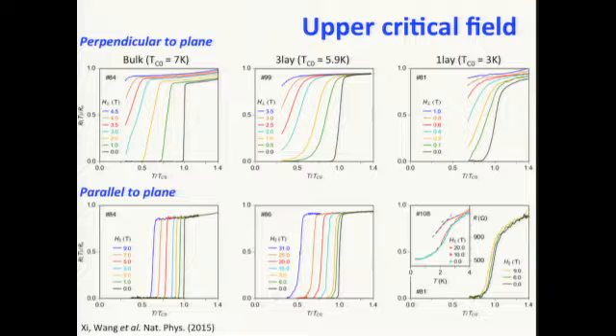The B field required to quench superconductivity in the monolayer is somewhat lower because of the lower TC in the material. On the other hand, if we put the material under a parallel magnetic field, the material turns out to be more resistant to the application of an external magnetic field. What I mean is that under 9 Tesla, for the bulk material, the TC dropped by about 40%. For the 3-layer material, the TC only dropped by less than 10% under 9 Tesla, and in fact it drops to about 50% of the original value under 31 Tesla. So it's very resistive to the external magnetic field. For the monolayer case, at 9 Tesla it changes by about 5% or so, barely changes.